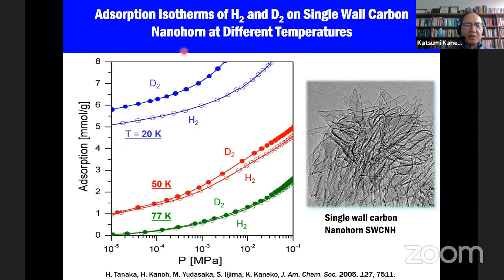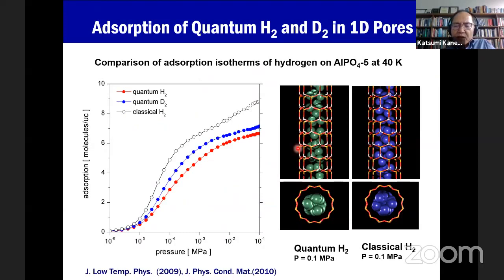Then Hideki observed this kind of very great difference on single carbon nanohorns at 20 Kelvins, where the smaller deuterium is more adsorbed. But this difference becomes slight with increasing temperature, but is still meaningful at 77 Kelvin. Such a difference is very typically shown in a simulation done by Hideki, and this is not carbon, but AlPO4-5.